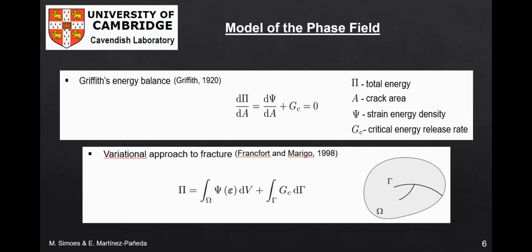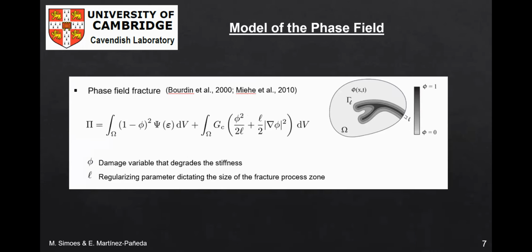Therefore, crack nucleation and growth can be predicted naturally without ad hoc criteria, as dictated by the minimization of this energy conservation statement. However, minimization of the Griffith functional is hindered by the fact that the crack surface gamma is unknown. And here is where the phase field paradigm comes to our rescue, because we can use the phase field as a marker, transforming the surface integral into a volume integral, enabling us to solve this global minimality problem.